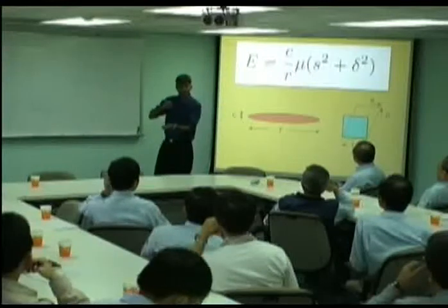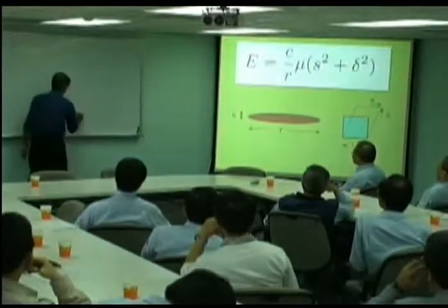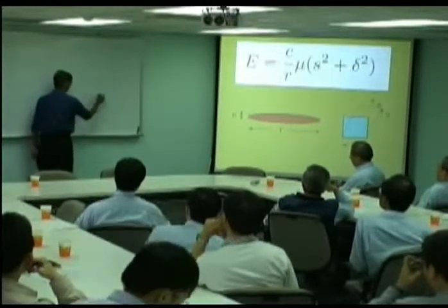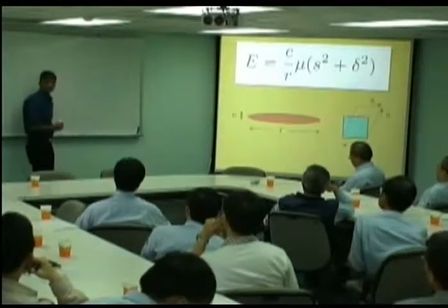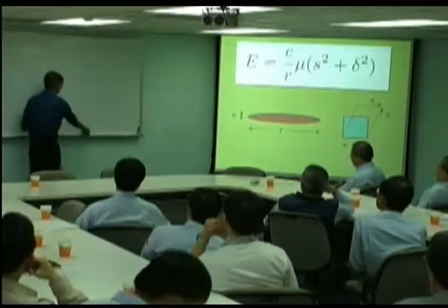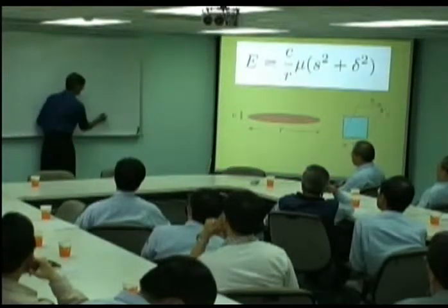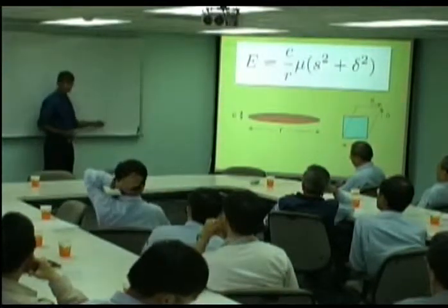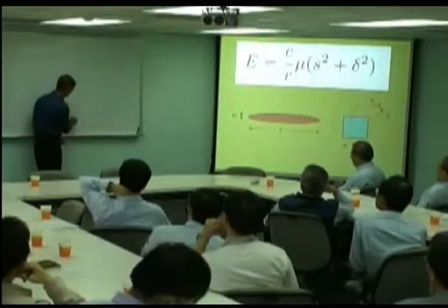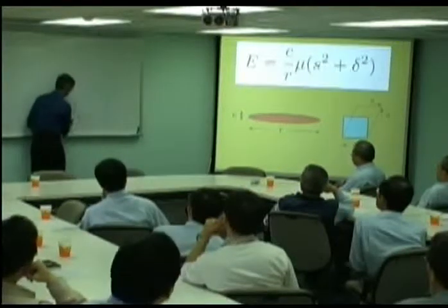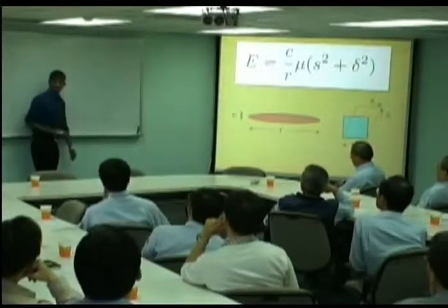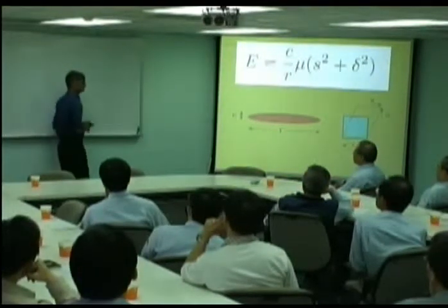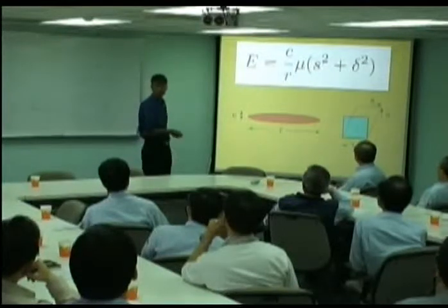Now, why do we have the thickness to length ratio? Well, if this is my austenite and I transform it to bainite, that's the shape change, and you can see these displacements here, they increase as I move away from this plane. So if I make this into a thin plate, then the displacement is very small, isn't it? And that's the reason why the best shape to minimize the strain energy is a thin plate.